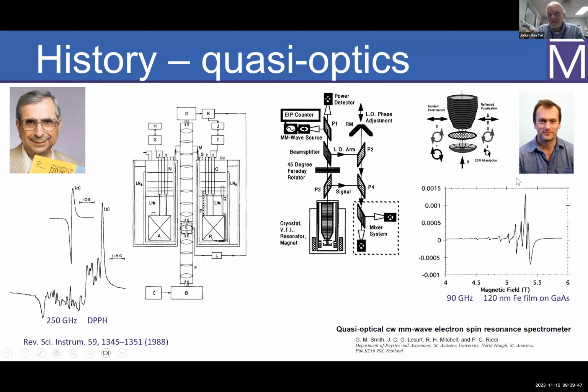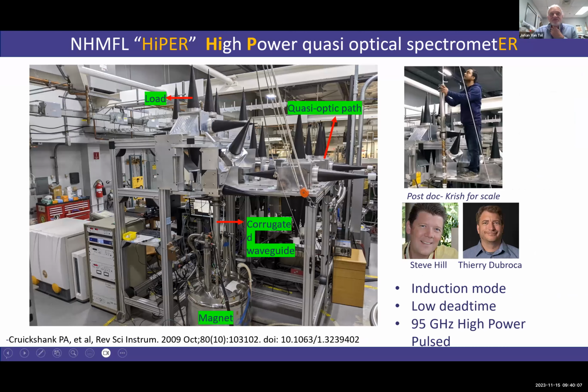And of course, a nice example of this is a ferromagnetic film, where you see the standing spin wave spectrum. The spectrum will actually depend on the thickness of the film because it's an interference of the spin waves within the sample. From there, I think things really took off, and a lot of spectrometers are now quasi-optic.